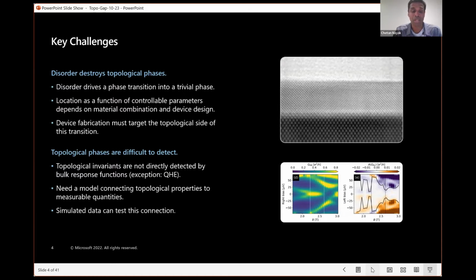That's problem number one. The second problem is that topological phases are difficult to detect. Topological invariants are not, in general, directly detected by bulk response functions. The quantum Hall effect is an exception. So those are the easiest things to measure. And so you need some model that connects the topological properties to measurable quantities. However, simulated data can test that connection. So there's some model-dependent and device-dependent translation from what you measure to topological invariants, and we can test those through simulations if we have a good model of the device. Okay, so those are the two key challenges, and those are the things that we've solved in this work, and that's what I'm going to tell you about.